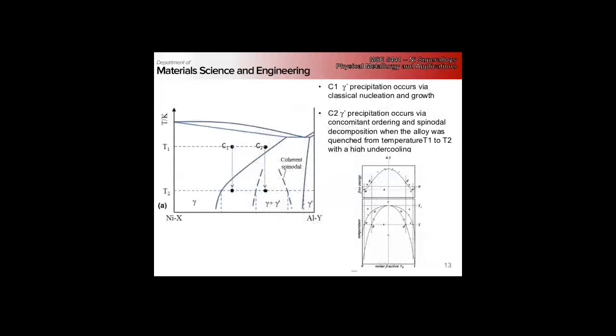If we're only slightly saturated or have a fairly slow cool, we get gamma prime precipitation following classical nucleation and growth theory. If we come over closer to the phase line and we come down more in the center of the two-phase region, we can get spinodal decomposition, right? We get a phase separation rather than nucleation and growth. So this is local ordering and phase separation.